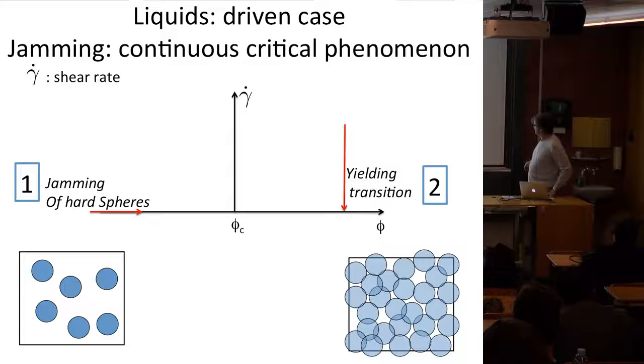And as you increase the packing fraction, as we will see, at some point, it becomes solid. There's another way to have a liquid-solid transition, if you're there in the phase diagram. So for example, a mayonnaise, if you push on it strongly enough, it would start flowing. So the strain rate tells you how fast it flows, and you can decrease the strain rate, and at some point, you become solid. And this, I will refer to as the yielding transition. Mayonnaise has a yield stress. At this point, the stress will have a finite value. If you go past this stress, it actually flows.